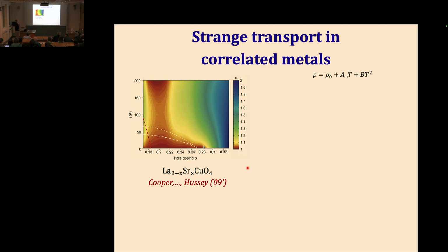So whatever is going on here in the normal state of the cuprate superconductor is not the quantum critical point for sure. If anything, it looks more like a quantum critical phase. There's an entire zero temperature phase, if you extrapolate, that seems to be a non-Fermi liquid. It violates the behavior that's expected for a Fermi liquid. And the other thing to note was noted a while ago by Nigel Hussey and collaborators, that this linear in T behavior seems to terminate not too far from where superconductivity actually disappears.